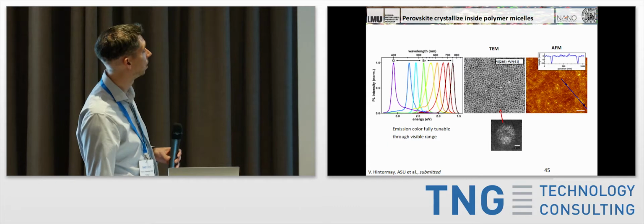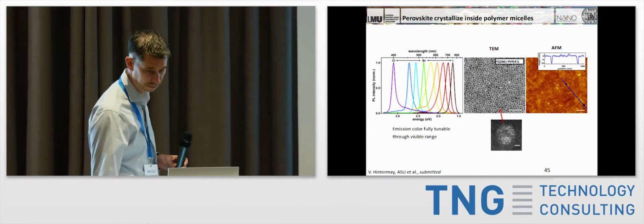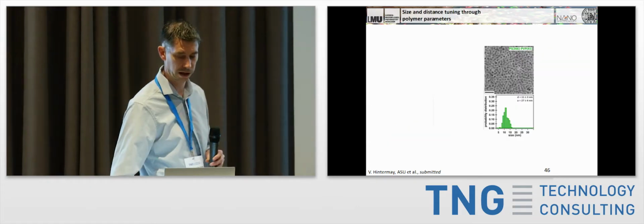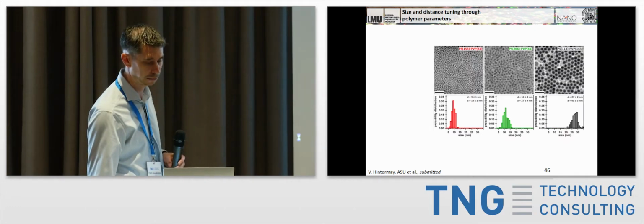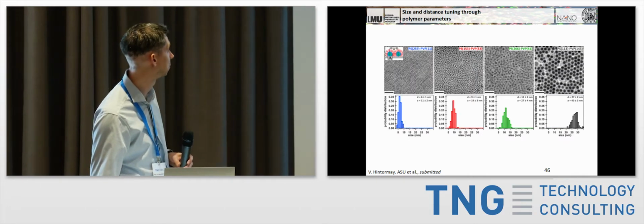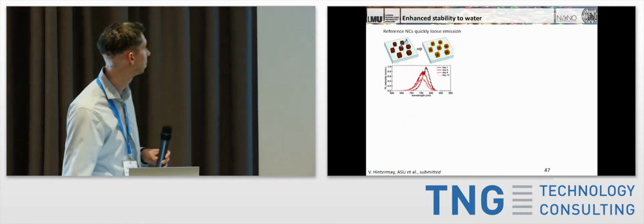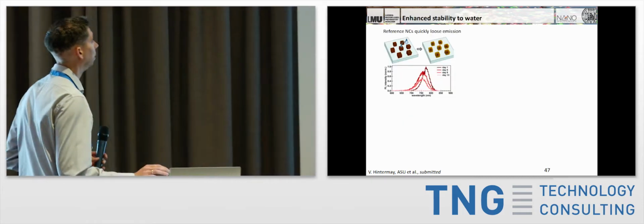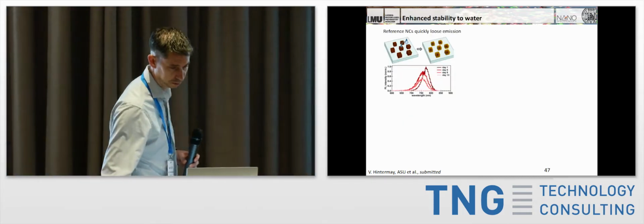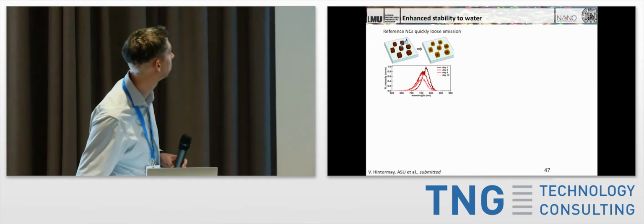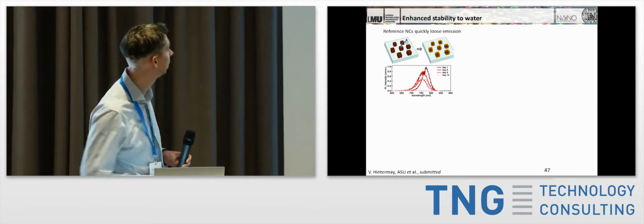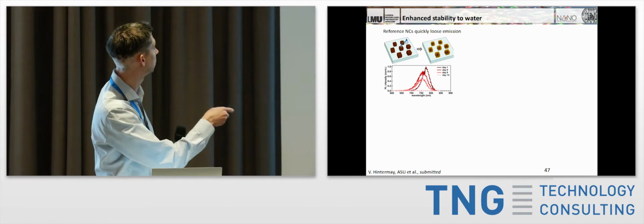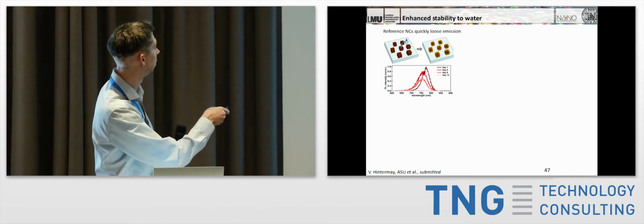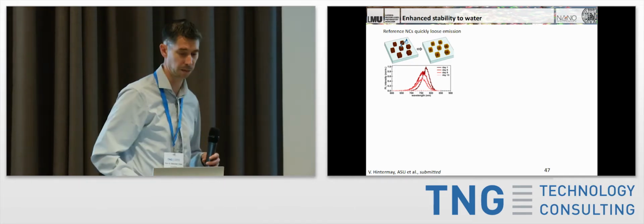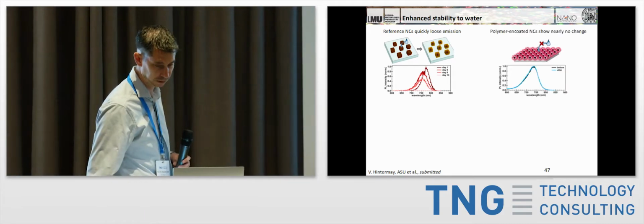You can tune the emission energies throughout the full range of the visible spectrum. So basically the same as you can do with other nanocrystals. You can do size tuning in them, which is important then also for getting into quantum confinement effects. But more importantly, they're stable, or more stable, to water. So if you look at just typical nanocrystals there, again, they degrade relatively quickly. These are just nanocrystals made without any of this polymer, and so within a couple of days, the total photoluminescence that's coming out of them vanishes down to 0.